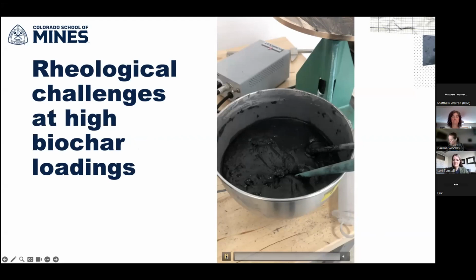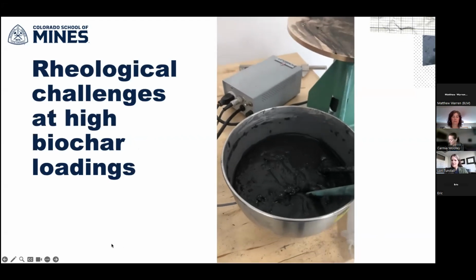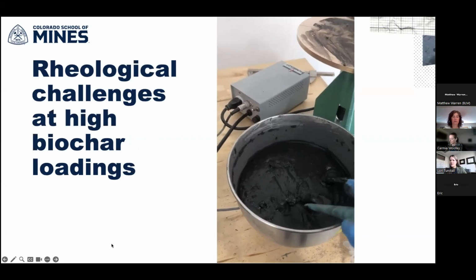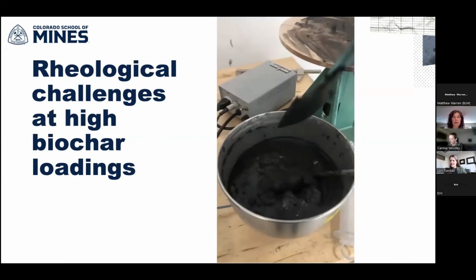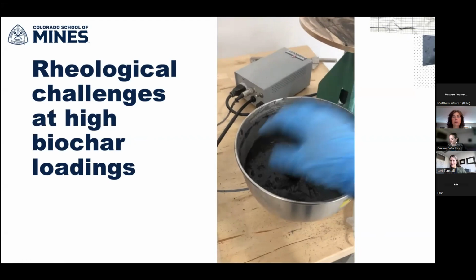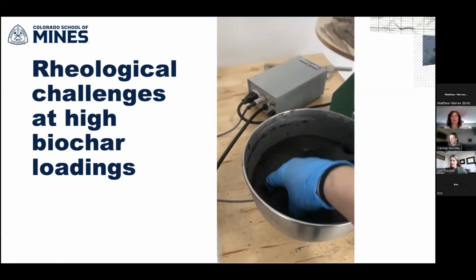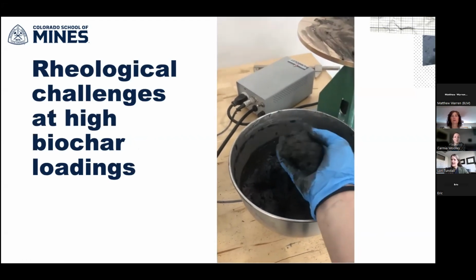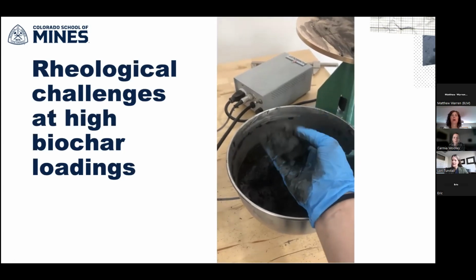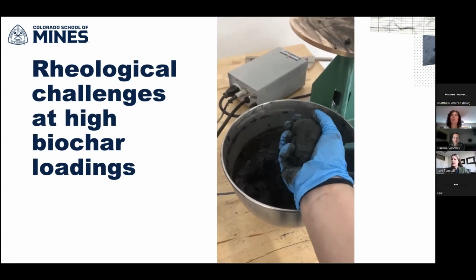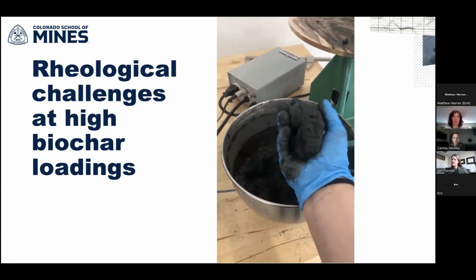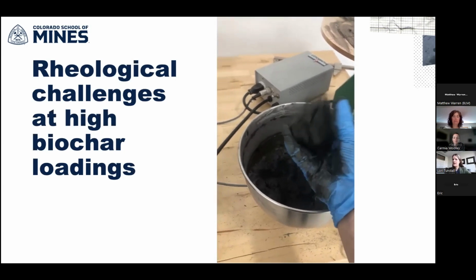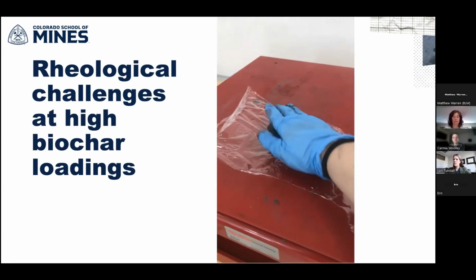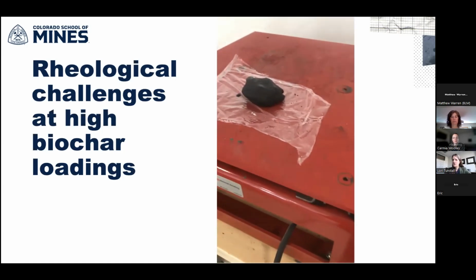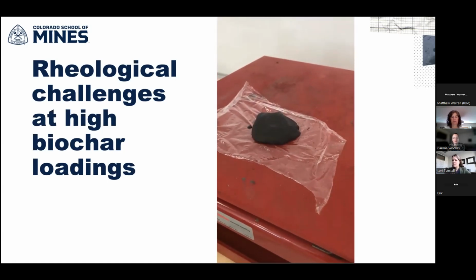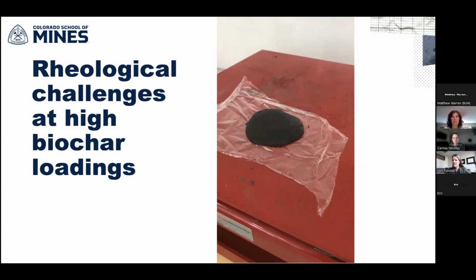So if you look at this, you can see just how stiff these mixes get. Right, this is not typical kind of concrete behavior. Typically, you can just pour it out, right? In this case, it's acting more like kinetic sand. There's a special term for this. The material tends to be shear thinning and shear thickening. So the interesting thing is that when you apply a little bit of vibration to it, the material flows. So this is a vibration table. So you can see that it flows really nicely.